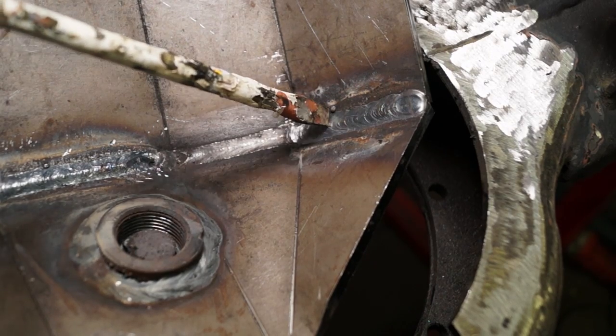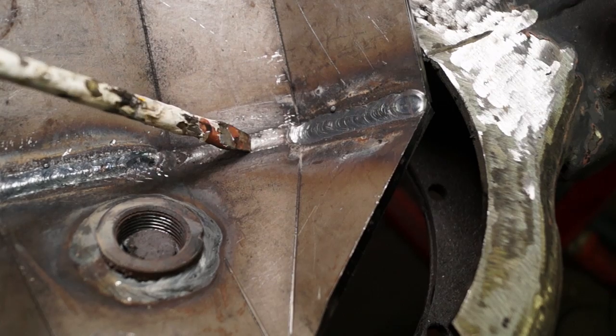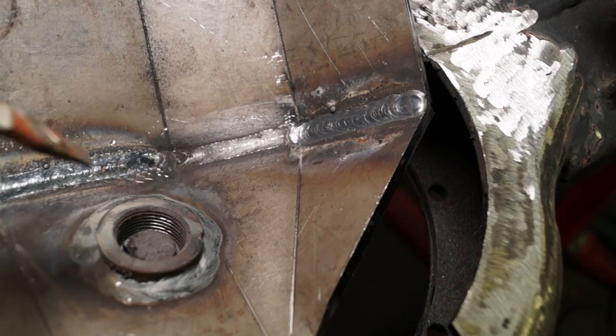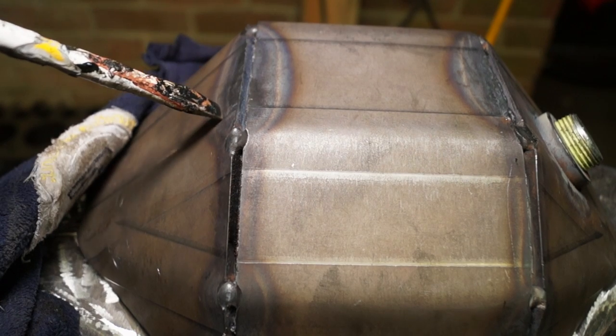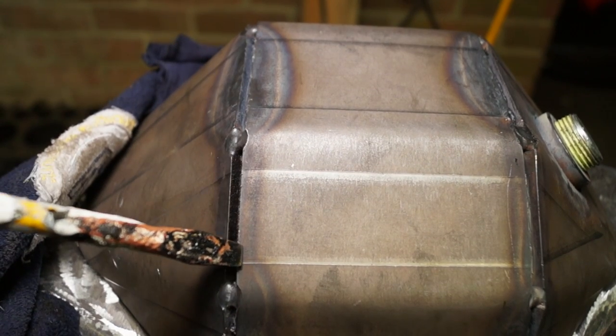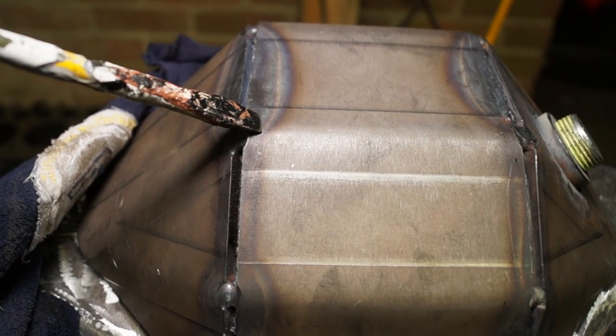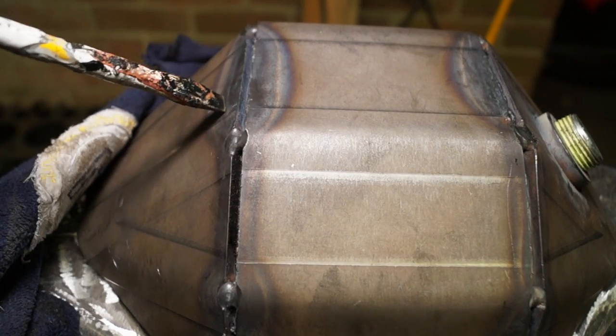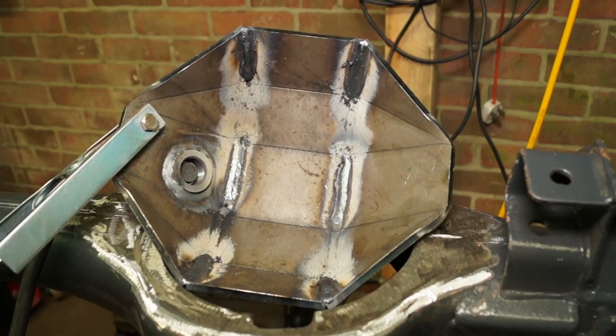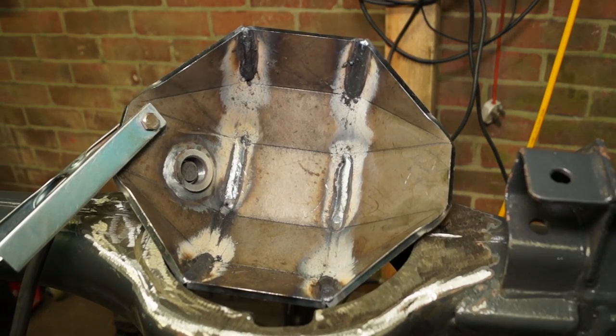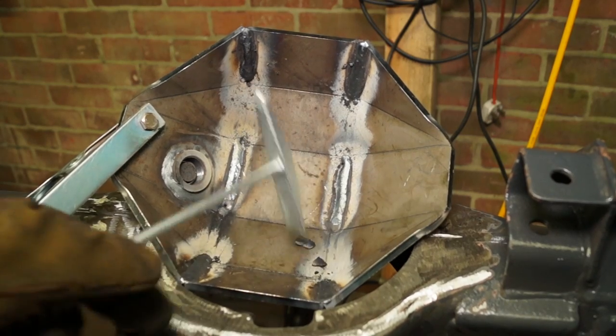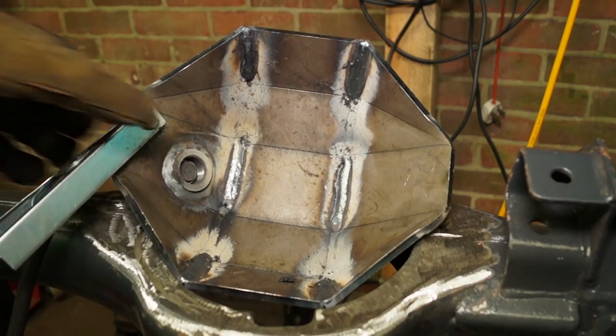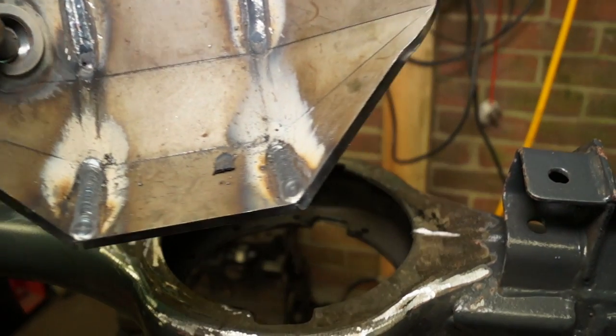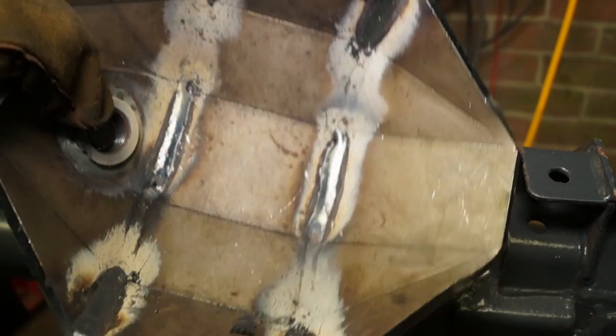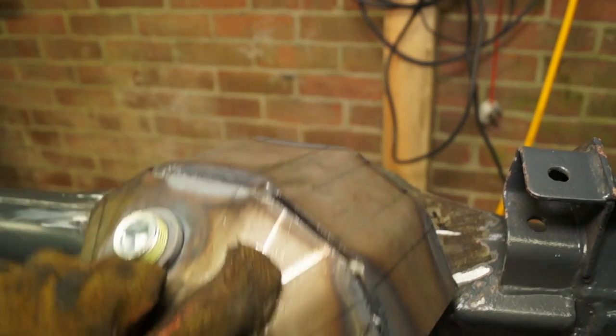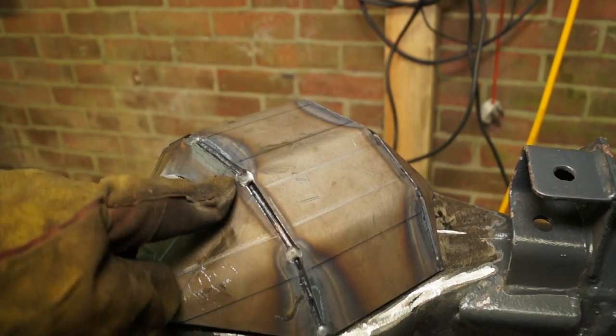Okay, it's only a little bit fatter than the MIG welding that was done on the inside by Gwyn Lewis. Now you can see the heat affected area is completely different between the MIG and the manual metal arc welding. Mine is much hotter. Basically, there's a lot more penetration with stick welding, and this is what we want. Preferably with the thicker steels, you want to be using a stick welder, and a domestic stick welder will do this easily at 100 amps, perhaps even 90 or 95 with a 3.25 rod.